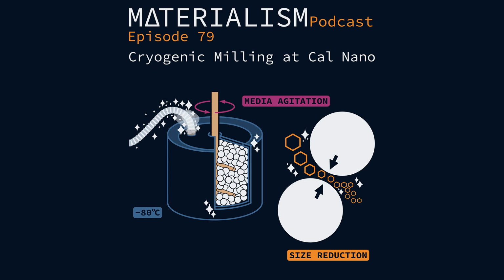Yeah, so one of the cool ones that we did a few years ago was we made this customized magnesium alloy that actually tested as the world record in terms of compression strength of any material. So what's so special? Why did it do that? It's basically from the grain refinement we get. We combine the magnesium with a couple of special sauce things.